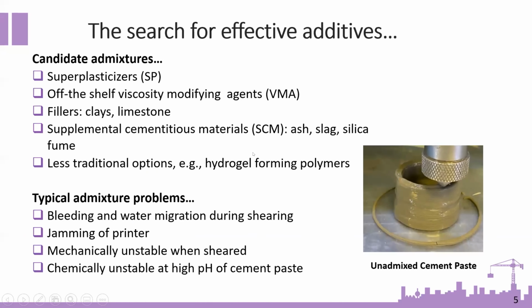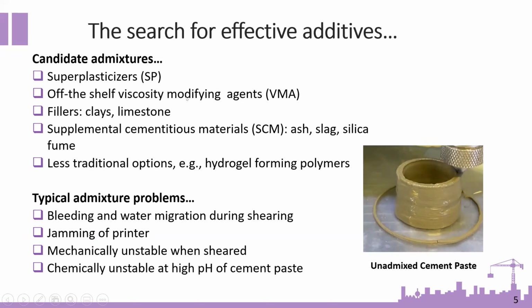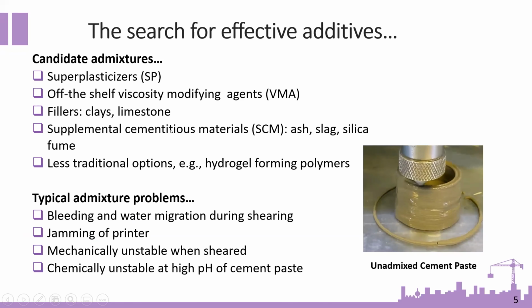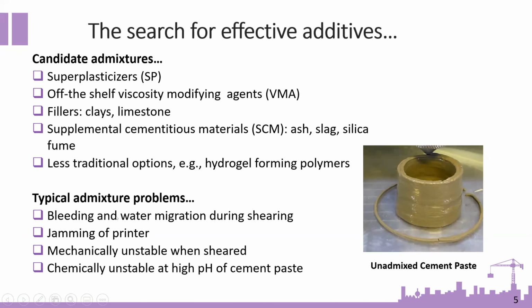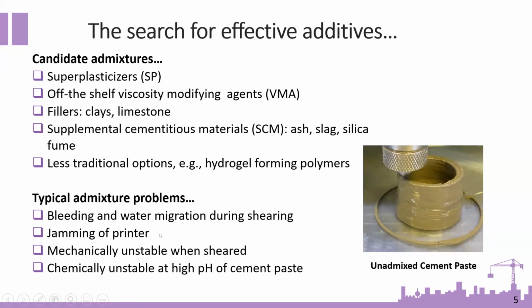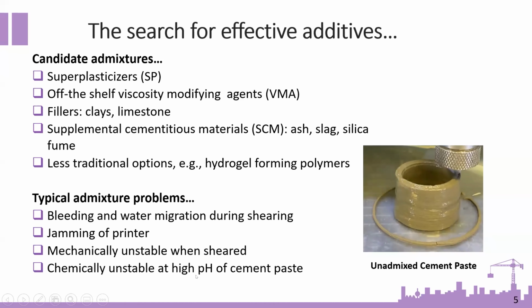We are searching for effective additives, and there are lots of candidates. There are traditional admixtures like superplasticizers or off-the-shelf viscosity modifying agents. People also use fillers like clays and limestones, and supplementary cementitious materials like ash, slag, and silica fume. There are also less traditional admixtures such as hydrogel forming polymers. There are some issues and problems with typical admixtures, including bleeding and water migration during shearing, jamming of the 3D printer, mechanically unstable behavior of these materials when they shear, and chemically unstable behavior at the high pH of cementitious materials. So we are looking for admixtures that solve these problems.